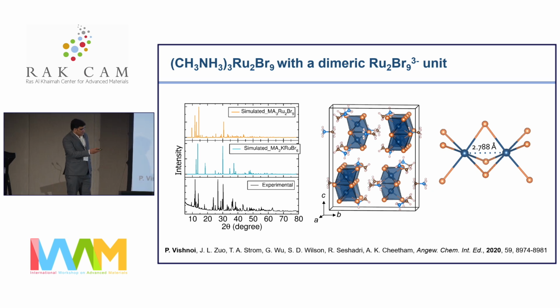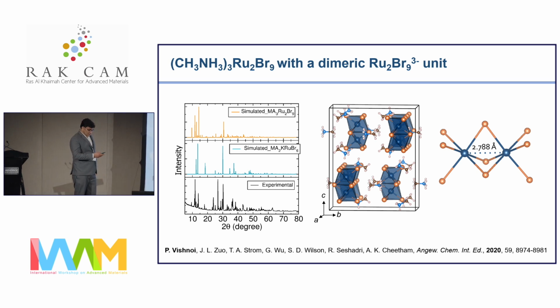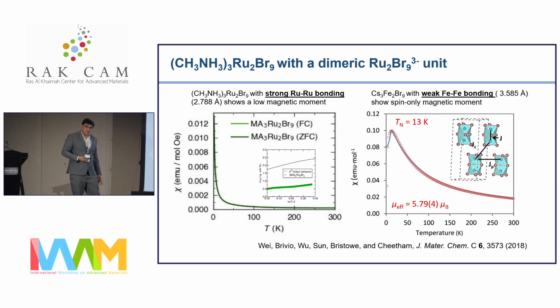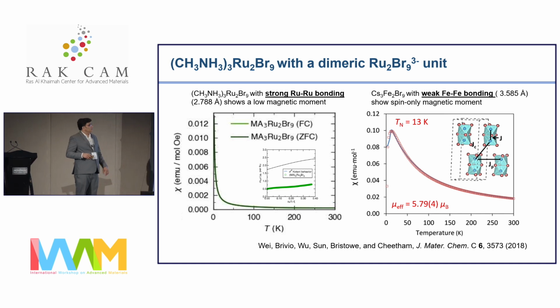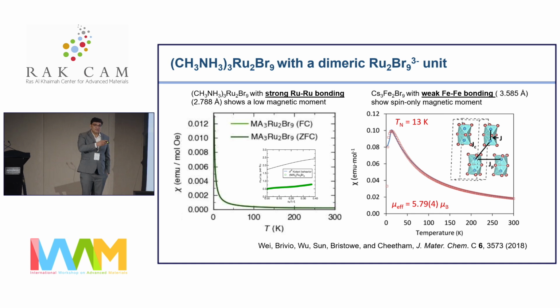Now, to mention here, the interesting fact is that the 3-2-9 phase contains a diruthenium Ru2Br9 dimer with a very short Ru distance, which is about 2.8 angstrom. This also means there is a ruthenium-ruthenium interaction. And as I mentioned, the ruthenium that we are using, Ru3+, has 1 unpaired spin. So when 2 ruthenium centers come closer with a short distance, the chances are that they might interact antiferromagnetically within the dimer and quench the magnetic moment. And we exactly see that in this form, the magnetic moment is nearly quenched, nearly diamagnetic.